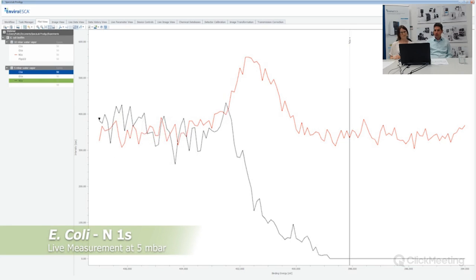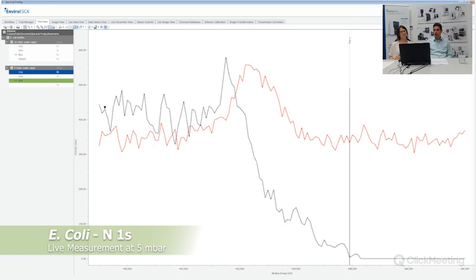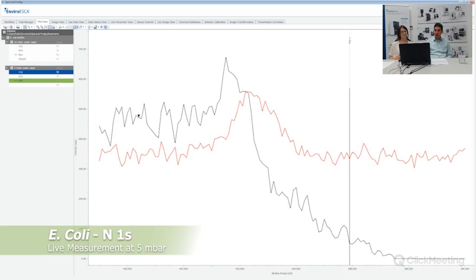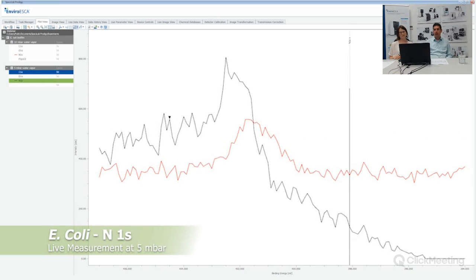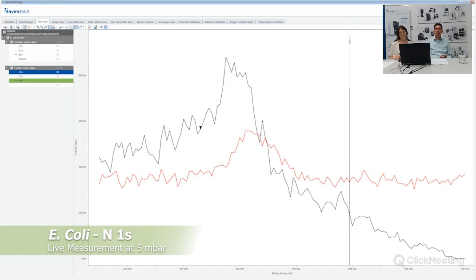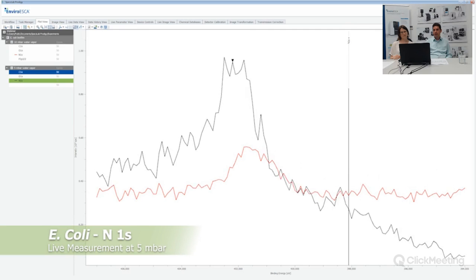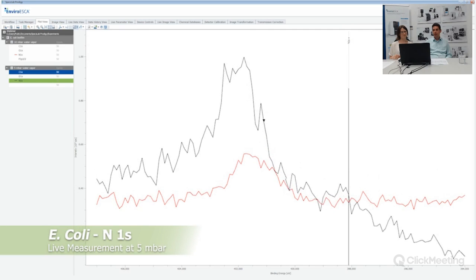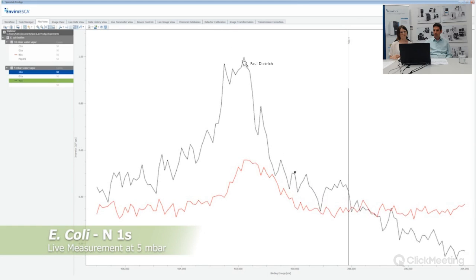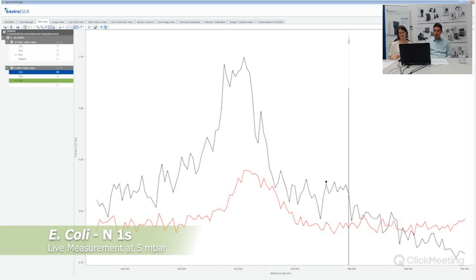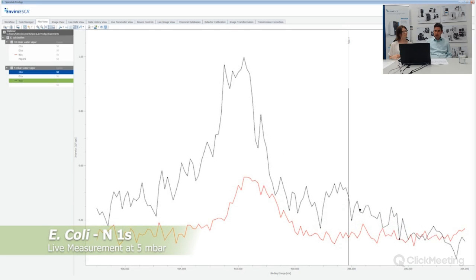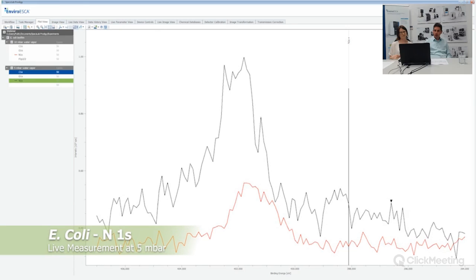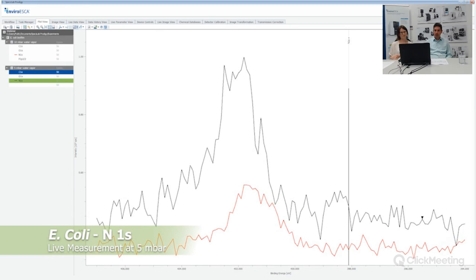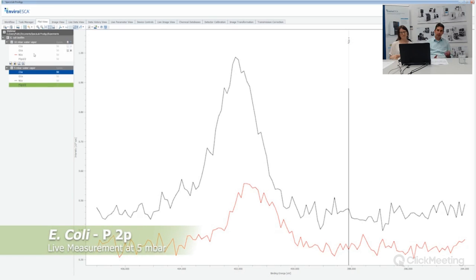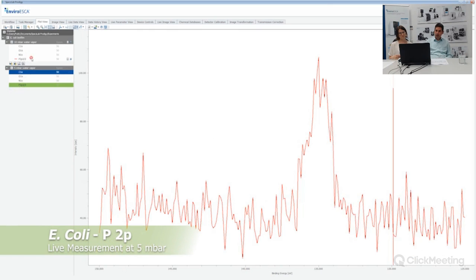Here now the nitrogen 1s spectrum at 5 millibar, and you see, as for all the other spectra, that they're a little bit shifted to higher binding energies. This is due to the environmental charge control: the gas pressure is reduced, and that's the same as what Andreas showed before on the PTFE sample. You see a slow shift in binding energy to higher binding energies due to a not as good charge compensation as before at 10 millibar of water vapor. But you see that the intensity is much increased. So this is a trade-off between signal intensity and the conditions you want to measure in.